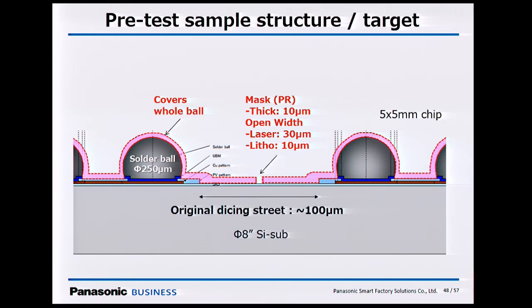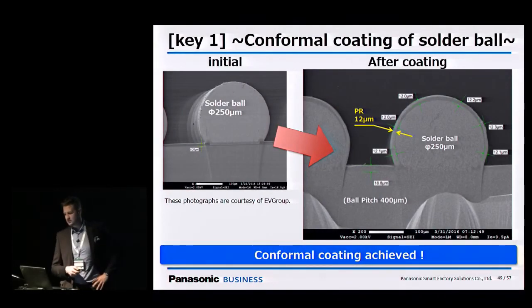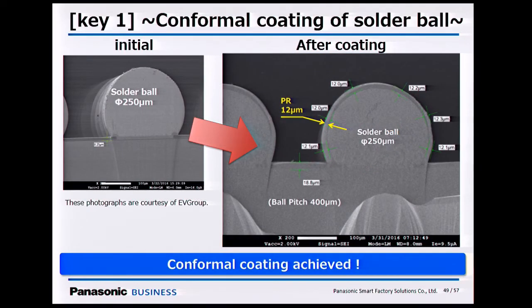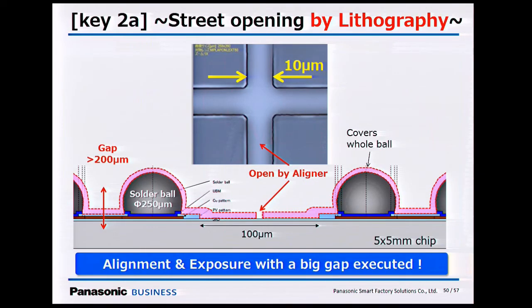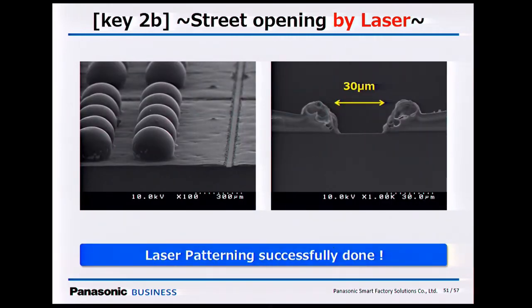But whether it's realistic or not, I'm not sure. But we can do it. We can at least dice it, etch it. So this was the example of conformal coating with the help of EVG. We were able to achieve 12 micrometers conformally coating all the way around the device in all areas, especially critical areas like here, and no wastage in this region. And yes, opening with 10 micrometers, no problem, and etching it, no problem. And same with laser. We can at least do 30, but as I said, smaller is also possible.